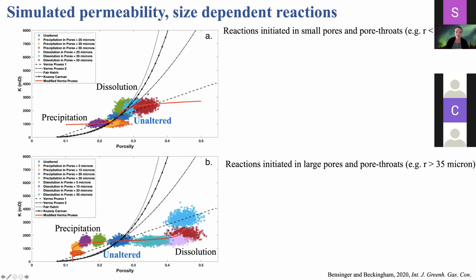When reactions are initiated in large pores and pore throats and then extend to smaller pores and pore throats, you have large changes in porosity due to dissolution and precipitation. And then once you start impacting the smaller pores and pore throats, you start having increases in permeability due to dissolution or decreases due to precipitation. And these are not captured either by these macroscopic porosity permeability relationships.